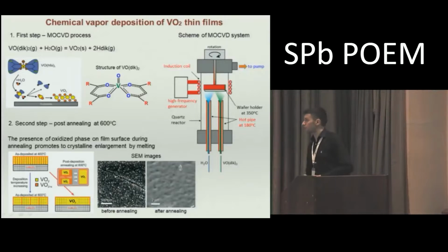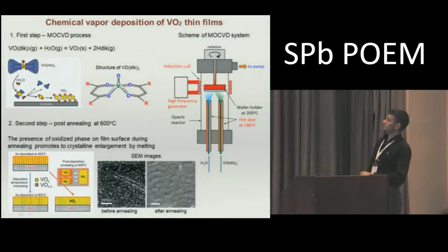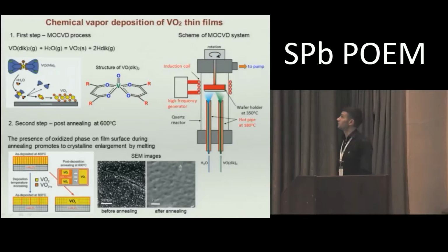The second step of our method is post-annealing at 600 degrees. During this process, we recrystallize our film. We increase the grain size of the vanadium dioxide and reduce the grain boundaries in this film. This is important because the morphology also affects the electrophysical characterization of our films. On the right part of the slide, you see our scheme of the reactor.